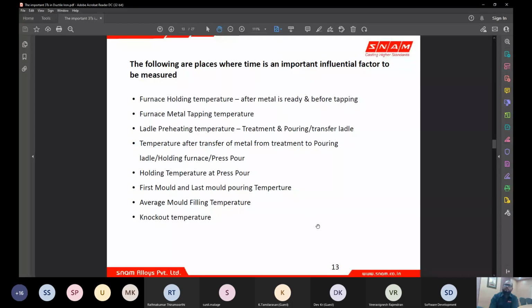So, furnace holding temperature, that means after the metal is ready and before tapping. As we had mentioned, the temperature at which we hold the metal matters a lot. We generally hold the metal close to melting temperature or slightly below, maybe for tapping temperature. This holding temperature again has an impact on the amount of nuclei present, and when you hold the metal for a longer time at a very high temperature than required, there is superheat, which is the amount of temperature above the melting point of the alloy.